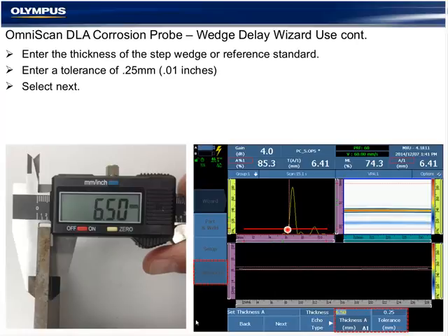The thickness that we're going to use for the wedge delay calibration or validation should either be a reference standard with a certification of known thickness, or more commonly, especially if it's a velocity other than carbon steel, mechanical calipers that we measure ourselves. We want that to be a precise number, not a nominal thickness.